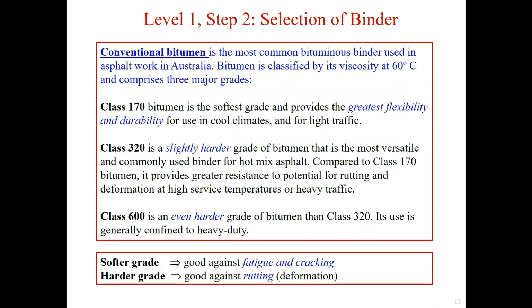The most commonly used bituminous binder in Australia is the conventional bitumen. According to its viscosity at 60 degrees, the conventional bitumen could be divided into three major grades: class 170, class 320, and class 600. The viscosity of the bitumen is a measure of its resistance to deformation at a given rate.